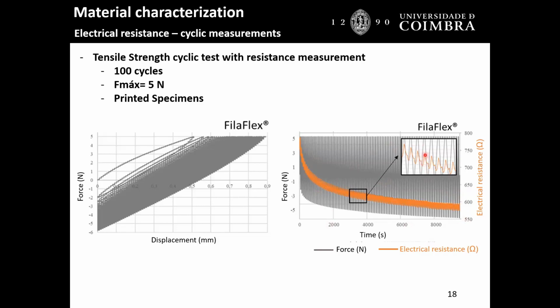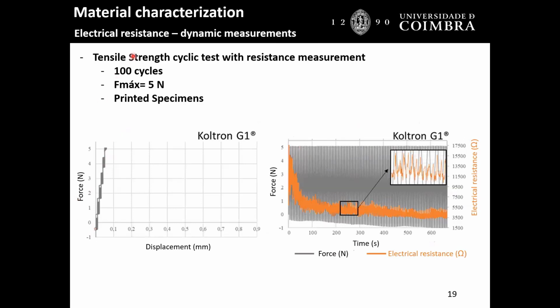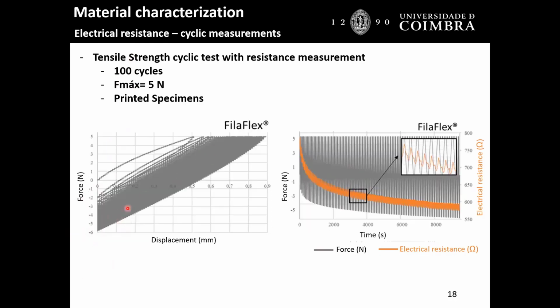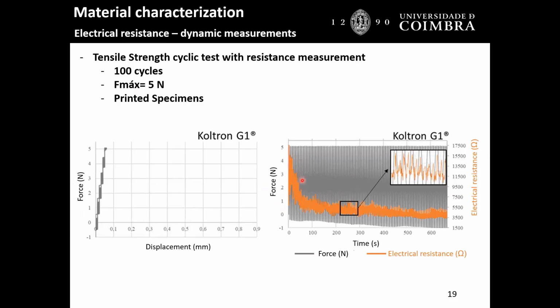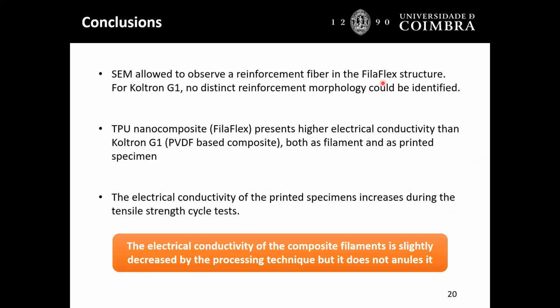And you see that you have a pattern in the values of the electric resistance when you apply force or when you remove the force during the cycle test, okay? In Koltron, of course, PVDF won't have the deformation that was presented before. I maintained the scale so you can see that this behavior is very different from this one. And also the main tendency is a decrease in the electric resistance, so an increase in electric conductivity, when you are making the cycle tests in your material.